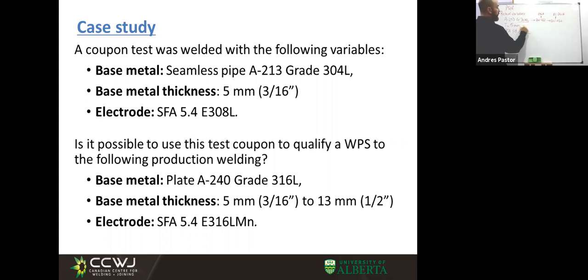So then I have to define the qualified range of base metal thickness. I have to go to the QW 451.1. So, and according to this thickness, define the minimum and maximum qualified. Okay. In this case, the range of thickness are from 1.5 millimeters to 10 millimeters. Okay. And finally, I have to define the F number. Okay. I have to go to the table QW 432 and define the F number. In this case, the F number is the F number 5. Okay?